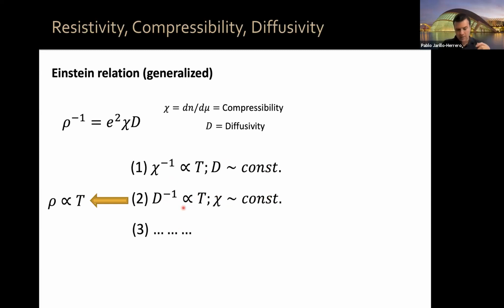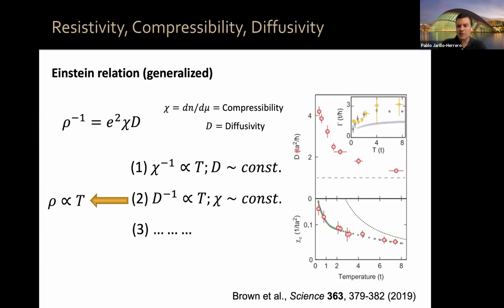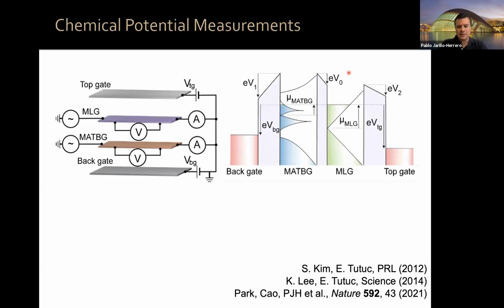So essentially this quantity, the electronic diffusivity of a system, had never been measured in solid state, to the best of my knowledge. The only measurement where people did measure the compressibility and the diffusivity at the same time, hence they could also measure the product resistivity, is for systems of ultra cold atoms recently. So we started to do these measurements now. For that we used a novel technique that was developed by the group of Emmanuel to measure the chemical potential of graphene initially. But now we adapted it to measure the chemical potential of magic angle bilayer graphene.